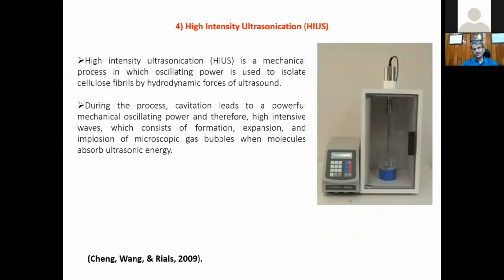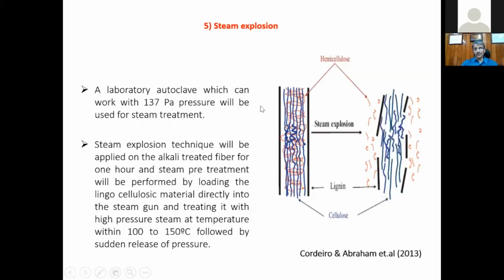In the high intensity ultrasonication process, you apply high mechanical force, where oscillating power is used to isolate cellulose fibers by the hydrodynamic forces of ultrasound. In the steam explosion process, you can see the natural fiber is subjected to high temperature and pressure in a jacketed system. We call it a steam explosion chamber. Then you suddenly release the pressure, and you have an explosion. The cellulose structure is opened up, and you have chemical hydrolysis of hemicellulose.